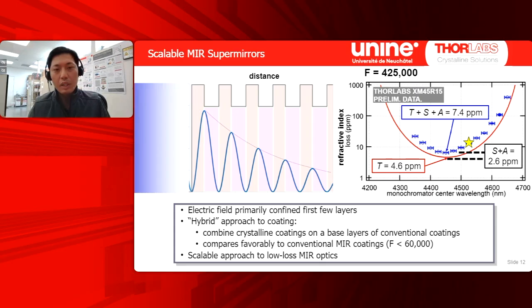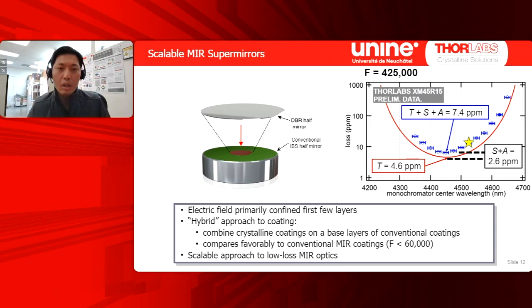That field decays quite rapidly, and most of the absorption is dictated by where the field is high. So what we can actually do is just make sure we use good materials for these first few layers. And although we do need many other backing layers to get the right transmission, the layers towards the end where the field has tailed off are not so important. And so this gives rise to what we call a hybrid coating, where you get the best of both worlds. You start with the optical substrate, you put down a conventionally coated half mirror, and that may use materials that are slightly more absorbing than our crystalline materials, but again, that's where the field is lowest. And then we overcoat this with our crystalline half mirror on top.